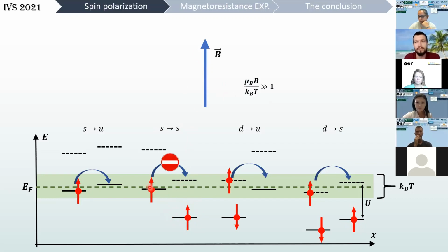As a consequence, the hopping between 2 singly occupied energy levels will be blocked by the Pauli exclusion principle. In addition, the hopping event between doubly occupied and unoccupied energy levels is related to that one by detailed balance. Then in steady state, this hopping will also disappear.